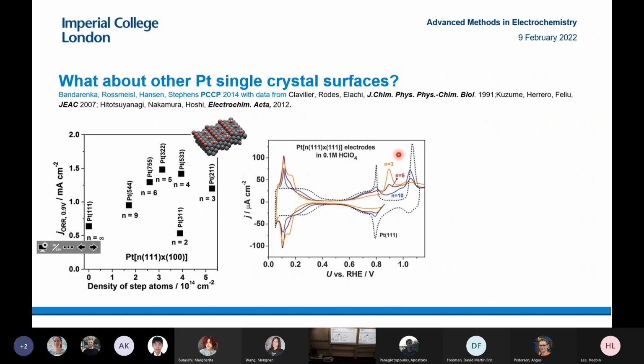And what we found was, when we look at the CVs of these step surfaces, so here we've got platinum 111, and then here, this is when you introduce steps. What tends to happen is a shift. Sorry, the OH adsorption peak in the CV tends to go to more positive potentials. And actually, what I think is that this peak here is the OH binding at the step, and this is OH at the terraces. So it's true that when you have introduced a step, you bind OH a lot stronger.